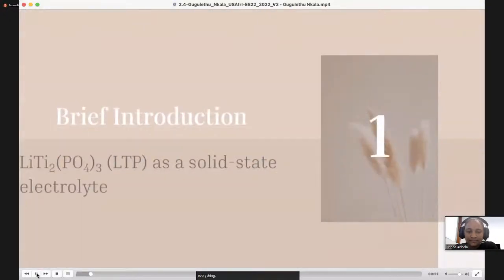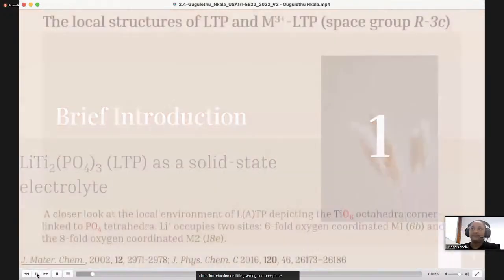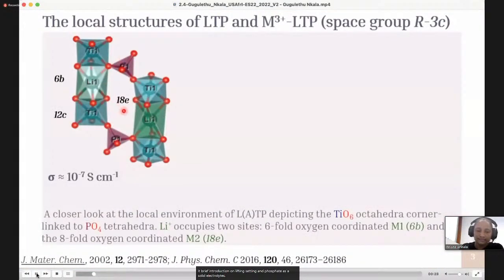A brief introduction on lithium titanium phosphate as a solid state electrolyte. The structure of lithium titanium phosphate consists of TiO6 octahedra that are corner linked to PO4 tetrahedra, forming a helix that extends mainly along the C direction. The mobile species lithium cations can occupy either the 6B or the 18E site. In this case, the 6B is more energetically favorable. The net ionic migration is from the 6B site through the lateral phase into the 18E cavity and into the 6B site on the adjacent ribbon.